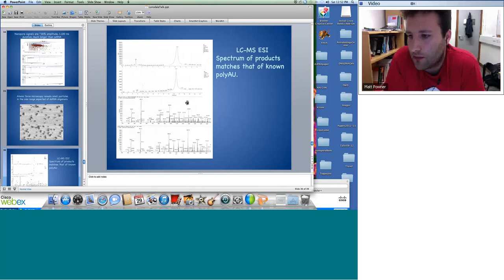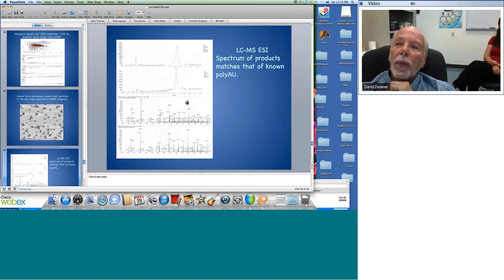You can lose it from ammonium, and the equilibrium is pushed by the volatilization of ammonia, which then increases the pH further. You don't actually specifically need ammonia present. You can lose it from ammonium by a general base catalyzed process. All you need is something to accept the proton, for example, your phosphate. I think the prediction of what you've just said is that there will be a pH change if we put ammonium chloride through one or more of these wet-dry cycles.